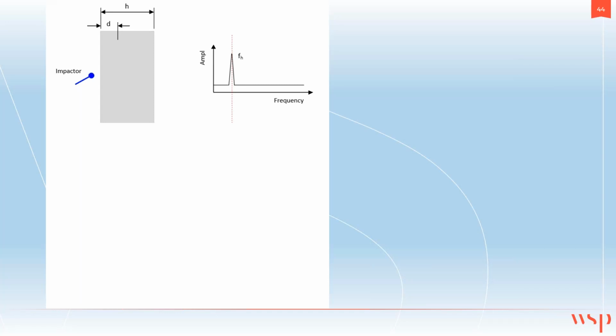This is the simplest case for impact echo application, which Mike talked about earlier. For a solid section of a concrete plate, which has no defect and no reinforcement, the spectrum is going to have a single dominant frequency, which we call thickness frequency, and it can be calculated using this equation.